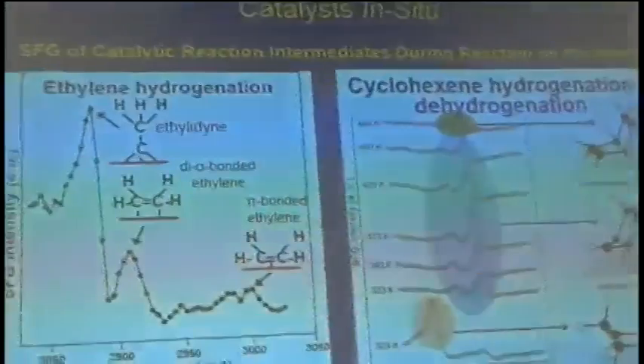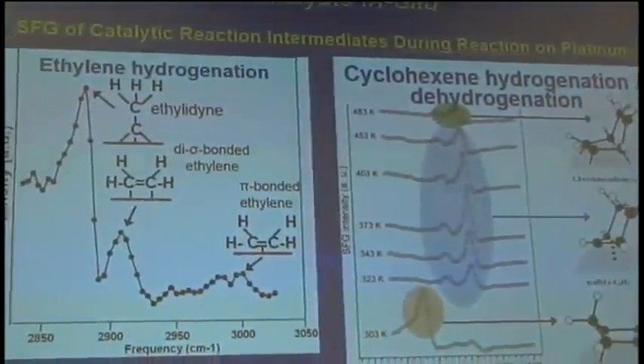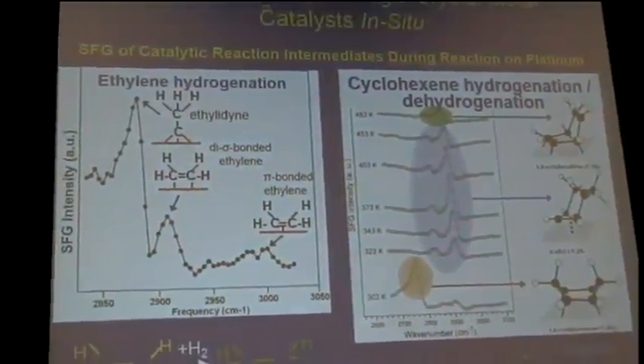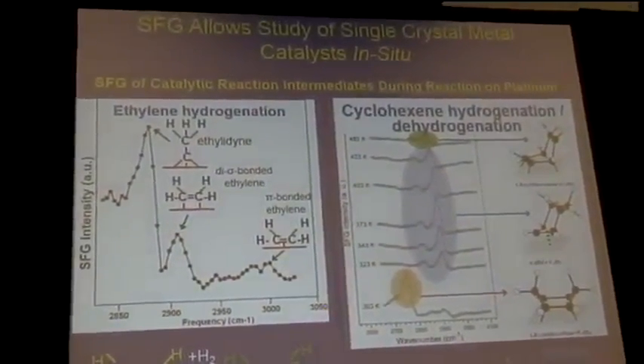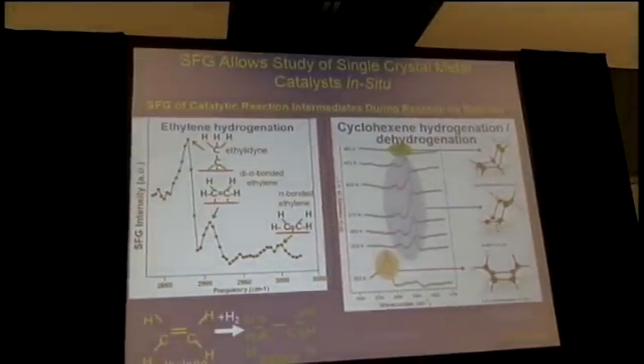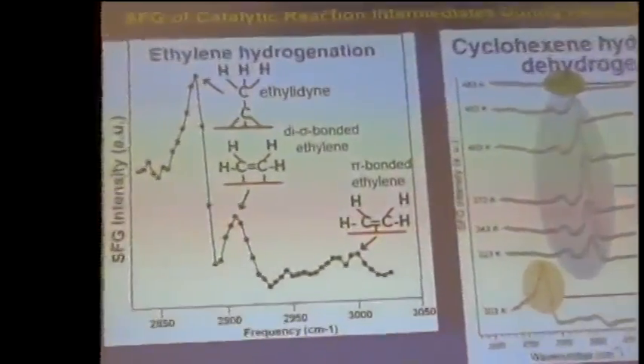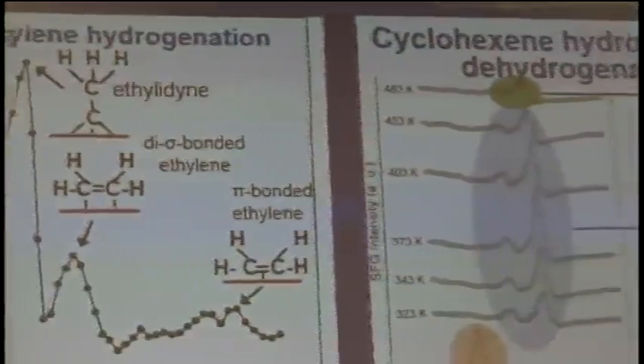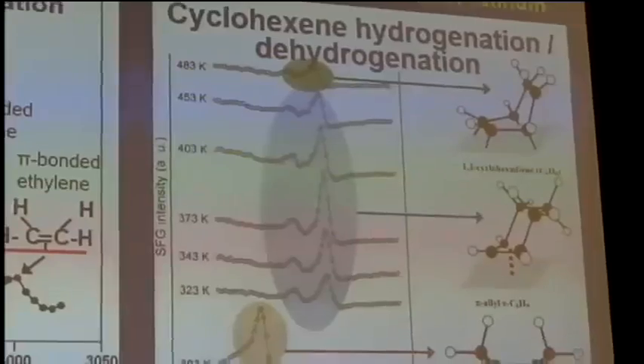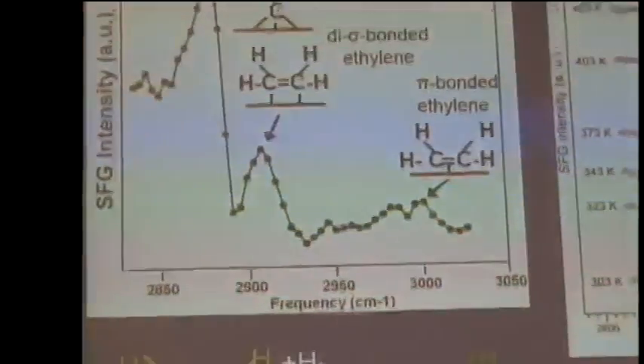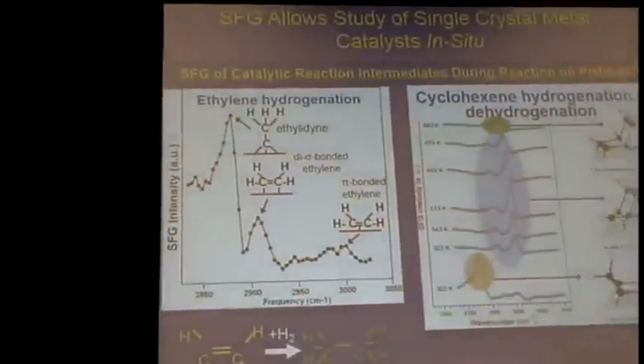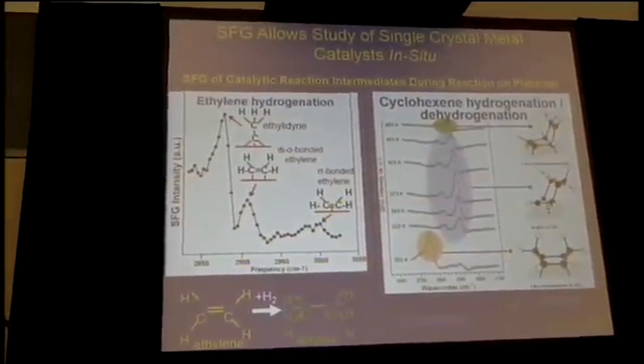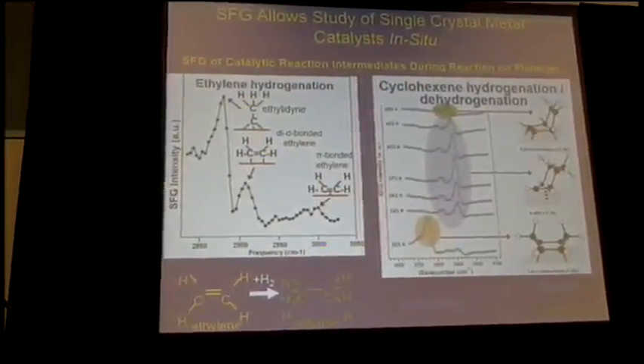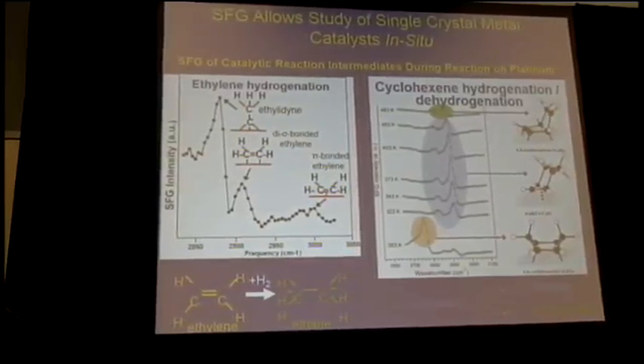If you look at ethylene hydrogenation, you can see 3 species on the surface. One is the one that turns over. These 2 are spectators. Okay, but you need isotope studies, etc., to distinguish. You see all 3 with vibration spectroscopy. If you do cyclohexene hydrogenation, you see the cyclohexadienes, 1,3 and 1,4 cyclohexadienes, and also these allyl reactions. The bottom line is we almost never see the product or the reactant, but we see something in between. But this is not exclusive. We have to do more to make this more conclusive.